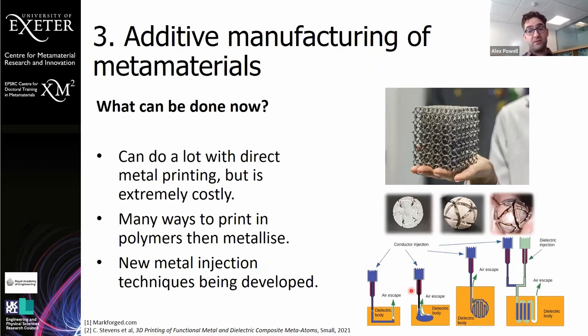But we can do a lot with direct metal printing. There are ways to overcome this overhang problem. If you design curves instead of right angle intersections, you're able to go a long way to not have problems with your overhangs. You can also print things at an angle to an extent. But the other problem with metallic printing is it's incredibly costly. So actually, as I said, it's often easier to make things in polymers and then metallize it, either by dip coating in a conductive paint or by doing that and then electroplating it.